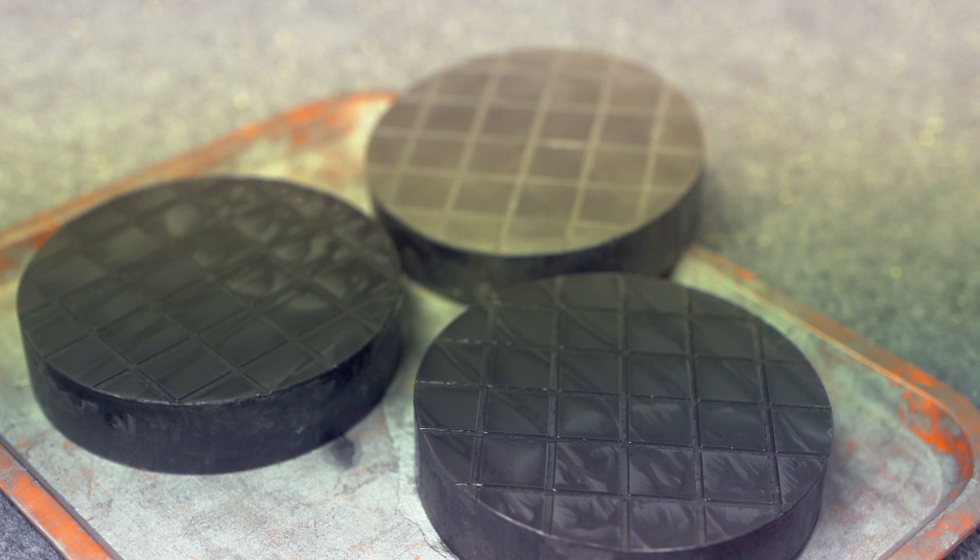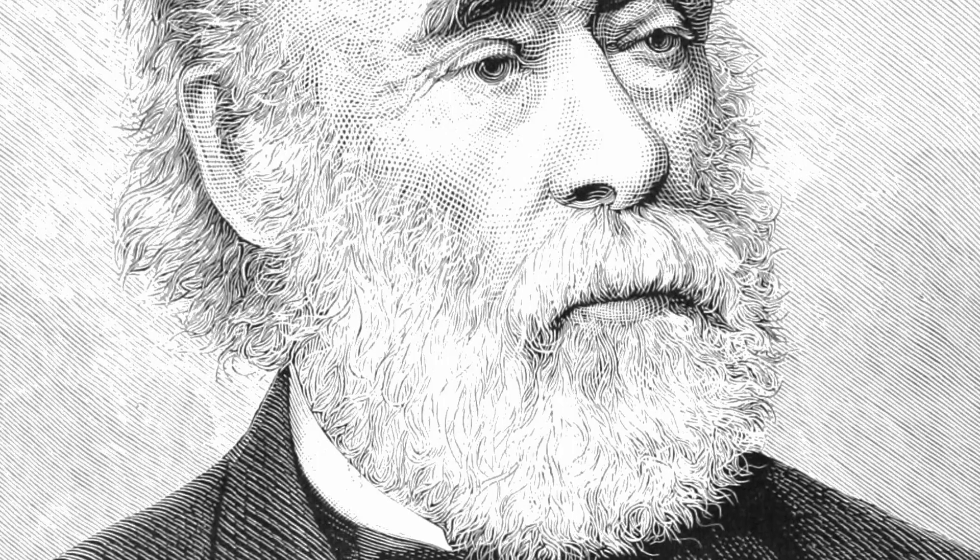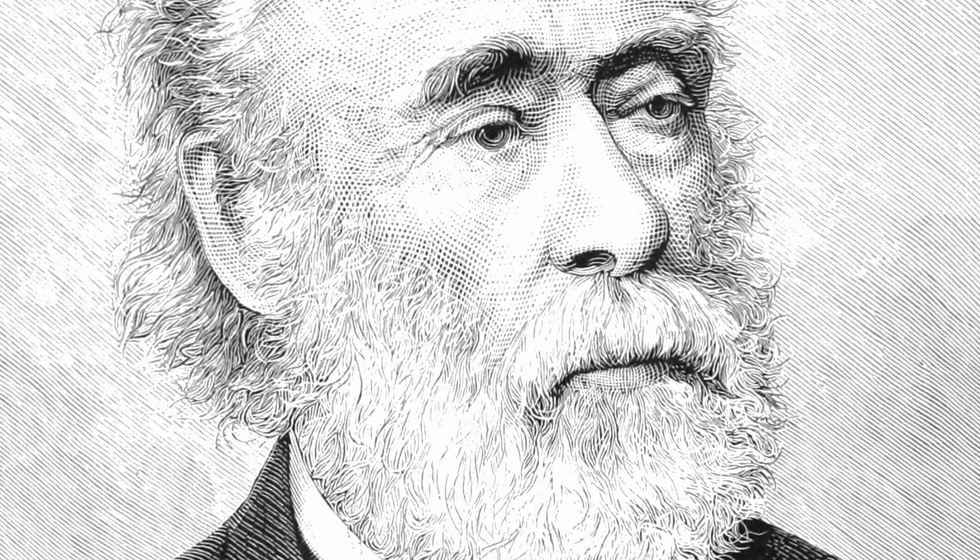A on B, B on C, C on A, over and over again. This method, called the three plate method, was initially invented by English engineer Joseph Whitworth, and allows you to create flat surfaces to incredible degrees of accuracy without any reference.